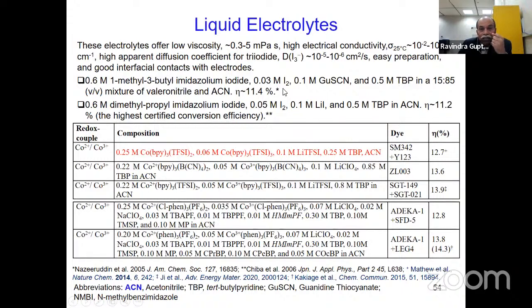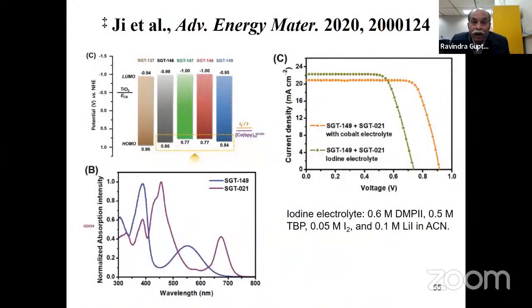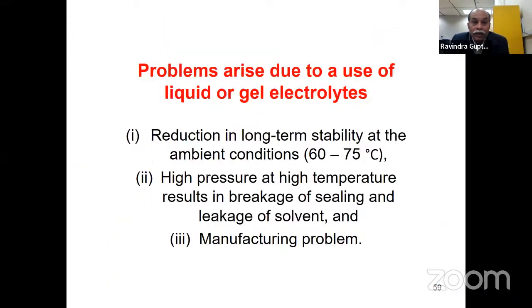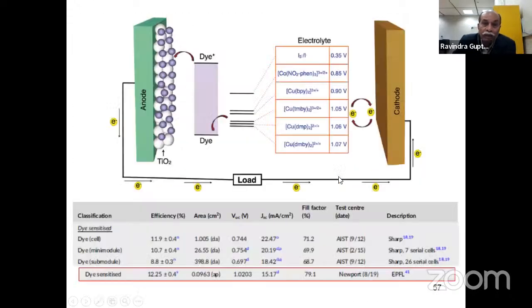This is iodide triiodide based electrolytes. When we go for the cobalt based electrolytes, efficiency is better than this. Even we have 14%, 14.3%. But the problem is these are liquid electrolytes. As Dr. Ansuman Dalvi told, we don't want liquid electrolyte. Why? Because we have so many problems: reduction in long-term stability, high pressure at high temperature results in breakage of sealing and leakage of solvent, as well as the manufacturing problem. So we don't want.